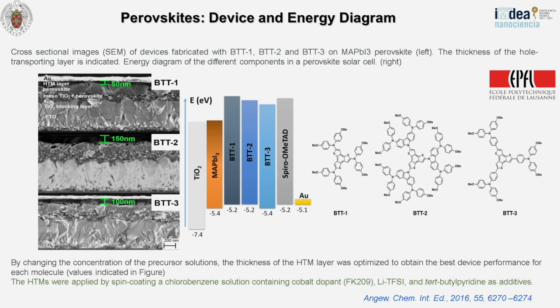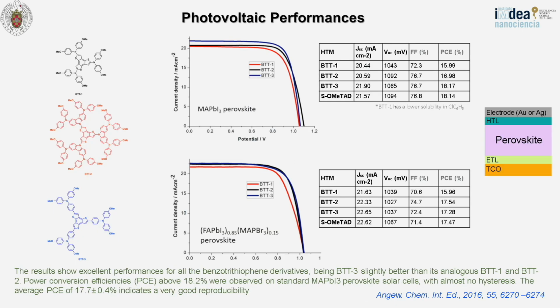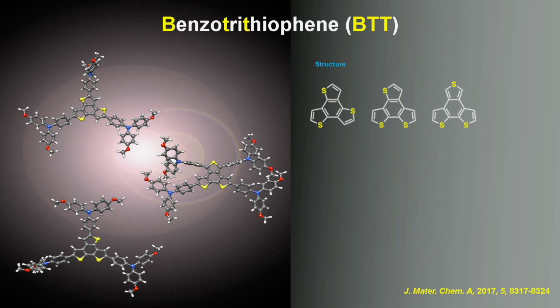And you see that all these BTT1, 2, and 3 have the right alignment in between the electrodes, the perovskite and the gold electrode. I will not go into detail, but we could discuss that later on. Here you have the photovoltaic parameters. It was published in 2016. And at that time, look at this, the efficiency was 18.17. I guess that the world record should be around 20%. No hysteresis was observed in this system. So they behave really very nicely, and equal to the spiro-OMeTAD material as well.